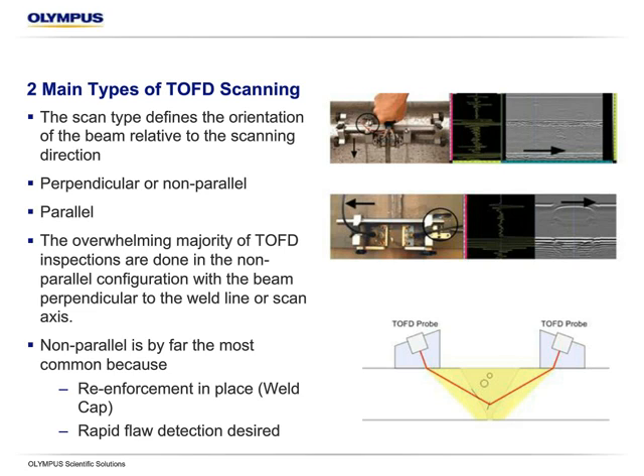The other type is the parallel. So we can see here the encoder has been switched to the same direction as the beam, and you're actually rastering across the weld or component. Now this obviously has a limitation that any weld reinforcement in place is not going to allow this to happen. So in a lot of cases we'll do a perpendicular scan, get a diagnosis, and then maybe a small amount of reinforcement may be removed to get a parallel scan. A parallel scan will give more accurate sizing capabilities, especially in the height plane, and it will also position the flaw very accurately as well, but it usually has that limitation.